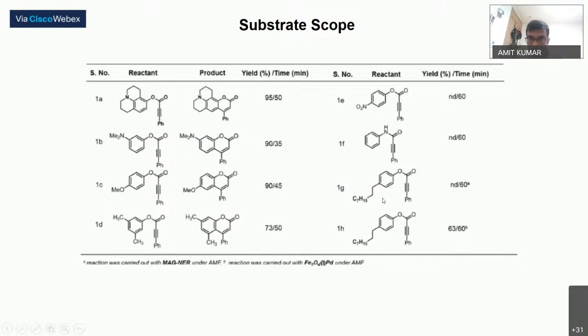And here, as you see, some substrates we used with the long chain, and long chains actually increase the bulkiness of the substrates, and with such a bulky chain, maybe these molecules cannot approach to the internal part of the nanoreactor. It proves that porosity of the silica is crucial for selective accessibility to the catalytic sites.